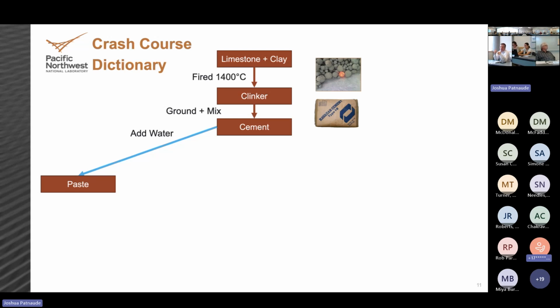Depending on where your cement is coming from and how strict that country or region's limits are on what constitutes a certain type of cement, a number of the additives that sometimes go into it are strictly there to fill up space and get costs down. Because if you can use only 90% cement and 10% filler that goes into a bag, well, every 11th bag of cement you produce is free for you. So in good practice, the North American and European cements are very controlled, very strict, defined by the Portland Cement Association or ASTM, what goes into it. But you start to get bags of stuff at Home Depot that was produced in Indonesia or in India or in China, and you see a lot more filler that goes into those mixtures.